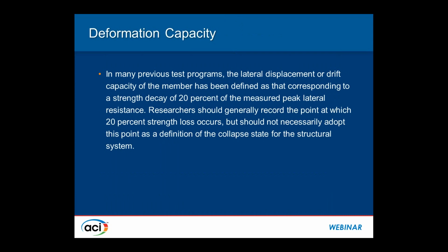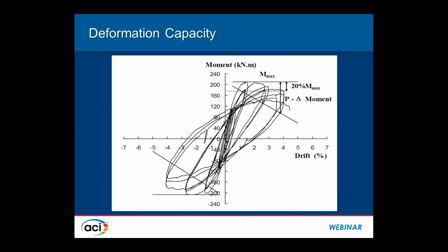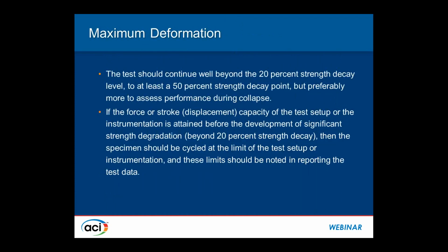Unlike bridges. In bridges, there's a little bit of redundancy, especially if you go to the extreme case of having a single-span bridge. 20% strength decay may be enough to bring the bridge to an unstable condition, whereas in buildings, 20% strength decay is tolerable before we declare that the member has failed. And this has to be indicated on the hysteretic relationship. And this 20% decay is often associated with not the first cycle, but the second or third cycle. If the member cannot maintain its strength during the second and third cycles without experiencing more than 20% strength decay, then it may be an indication of a failure point.